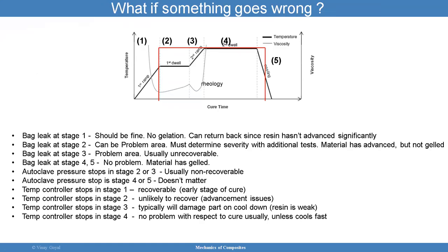So what if something goes wrong? What if something goes wrong at any of these stages here? All right, so something went wrong in stage one. So the good news is there was a bag leak. And I'm giving you examples from my experience. So say there's a bag leak at stage one. So I'm not able to keep vacuum. The good news is you should be fine. There's no gelation yet. You can return back since the resin really hasn't advanced in terms of polymeric cross-linking. So you can kind of start over again and redo your bag, the bag for the vacuum.